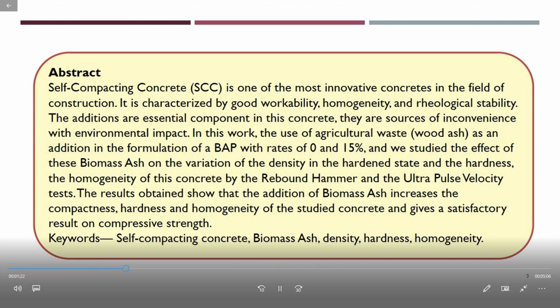They are a source of inconvenience with environmental impact. In this work, the use of agricultural waste, wood ash, as an addition in the formulation of a BAP with a rate of 0 and 15%, and we studied the effect of this biomass ash on the variation of the density in the hardened state and the homogeneity of this concrete by the rebound hammer and the ultrasonic pulse velocity tests. The results obtained show that the addition of biomass ash increases the compactness, hardness, and homogeneity of the studied concrete and gives satisfactory results on compressive strength.